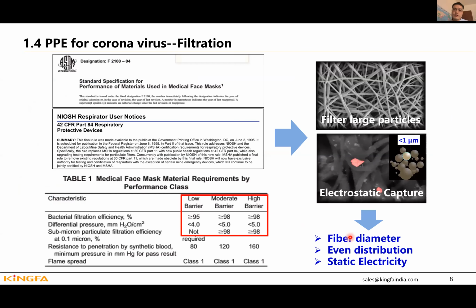So if we take a look at the microstructure of the melt-blown fabric, this is the microstructure. We can find the fiber is very thin. The diameter is about 25 microns, and so they can stop some big particles. And around the fiber, on the surface, they have some electrostatic charge, so they can capture some particles by the static electricity.